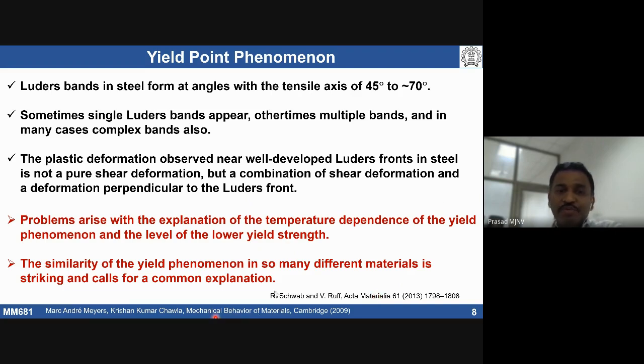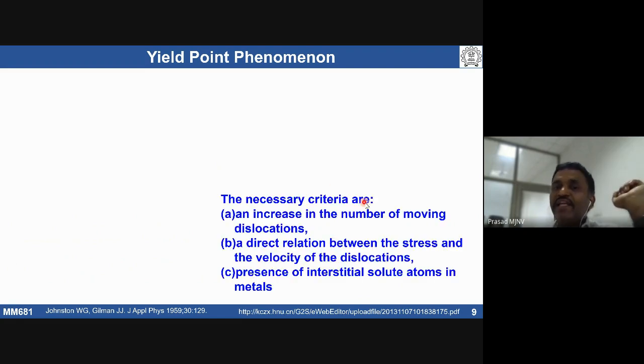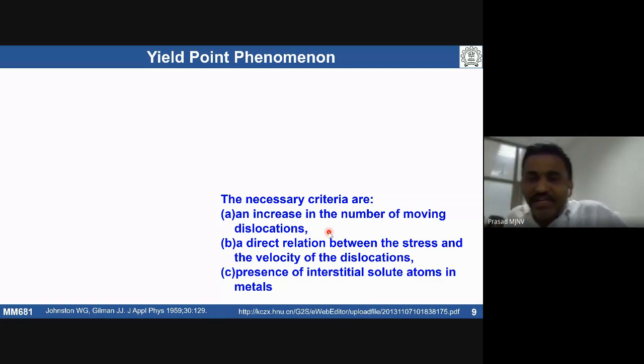So one of the so far common explanations is using Cottrell Bilby theory and Johnston Gilman models. According to Johnston Gilman theory, the necessary criteria are an increasing number of moving dislocations. One has to see the mobile dislocation density increase. That's one necessary criteria, and there should be a direct relation between the stress and the velocity of dislocations.